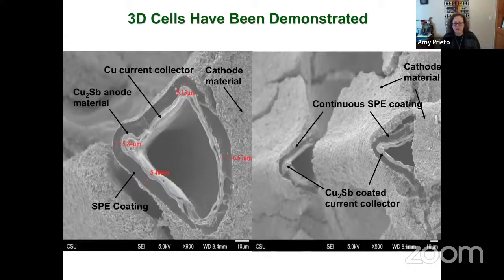We can freeze these in liquid nitrogen and cleave them. And here you're looking at a cross-section which really highlights some of the benefits of this architecture, but also some of the drawbacks. If you focus just on the image on the left, the first thing you notice is the copper foam is actually hollow. So the struts of the copper, because of how it's made, actually have some empty space. And we will need to be able to get rid of that in order to improve the overall energy density of the cell. You see the very thin layer of copper antimonide, the polymer electrolyte around it, and the cathode. And again, one of the advantages of electroplating is you can control how much material you plate for the anode side, and that's really important for capacity matching to the cathodes that we use.